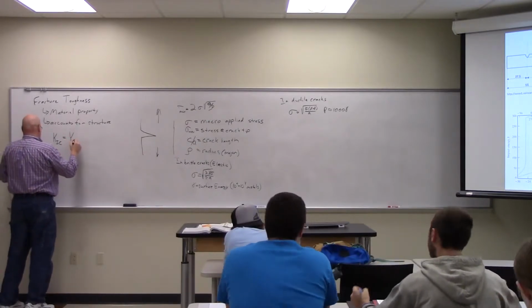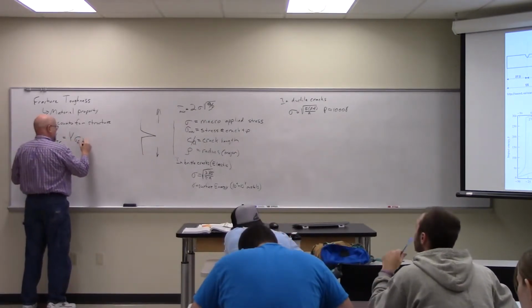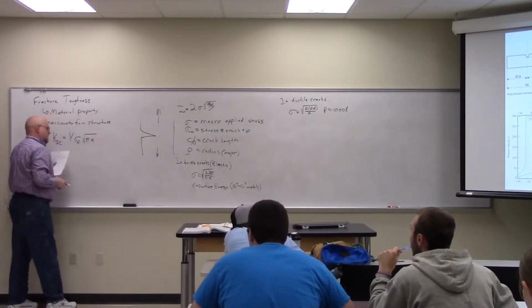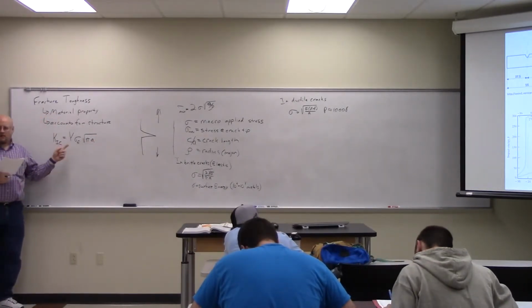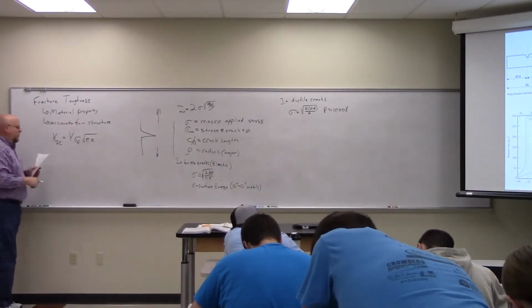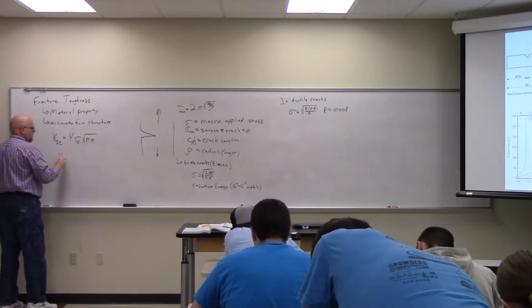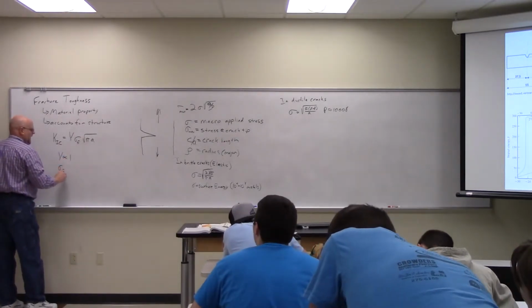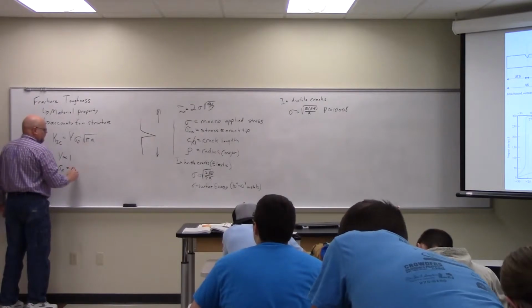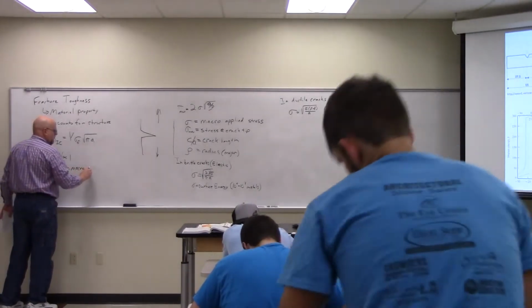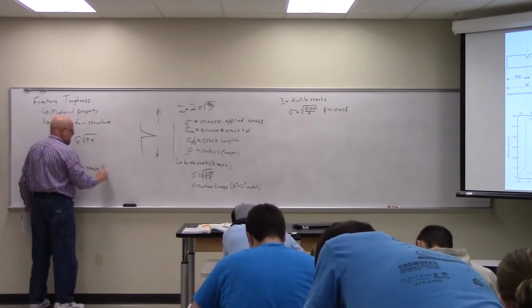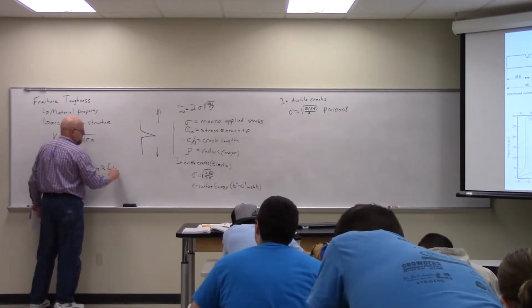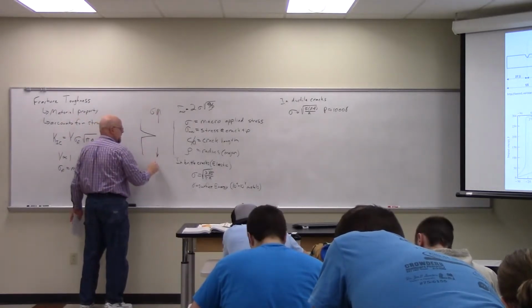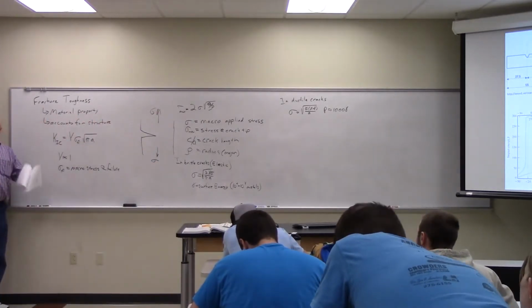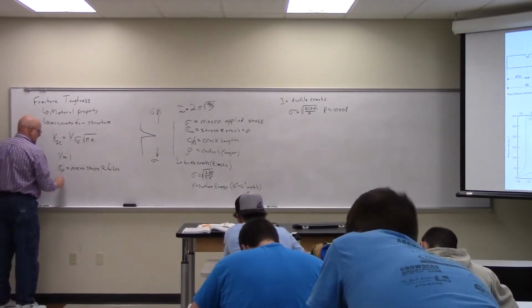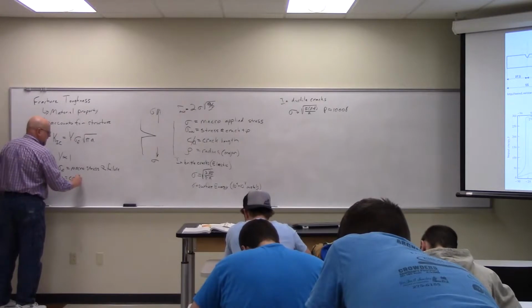And it's defined as Y times sigma f times the square root of pi times a. Y is an empirical parameter. It's on the order of 1. Sigma sub f is the macro stress at failure. In other words, that's the sigma that's applied out here, when you apply it to the sample. And then again, a is, as it was before, crack length.